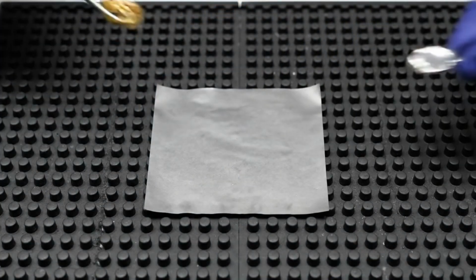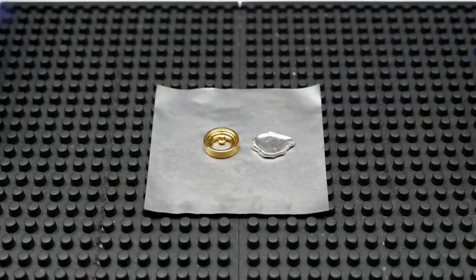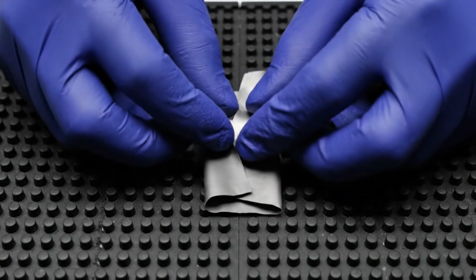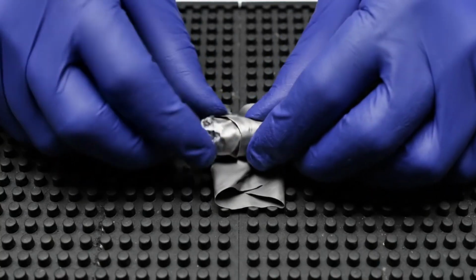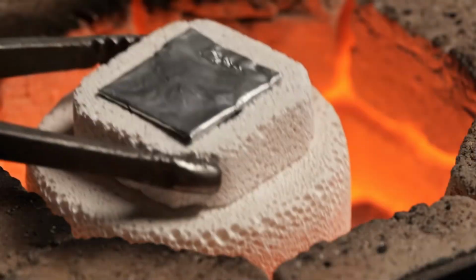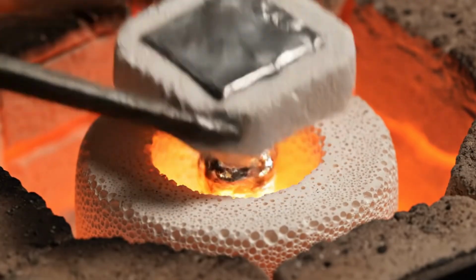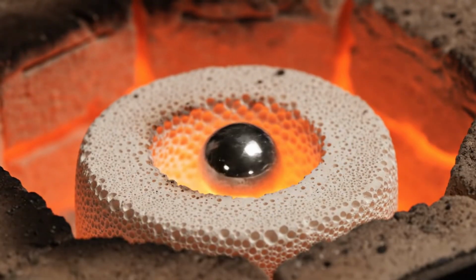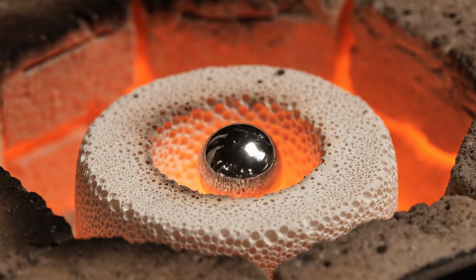The sample is wrapped in lead foil with silver, a preparation for the cupellation process that separates noble metals from any remaining base metal impurities. Placed into a porous bone ash cupel, the sample enters the assay furnace, heating up until the lead oxidizes and is absorbed into the cupel walls.